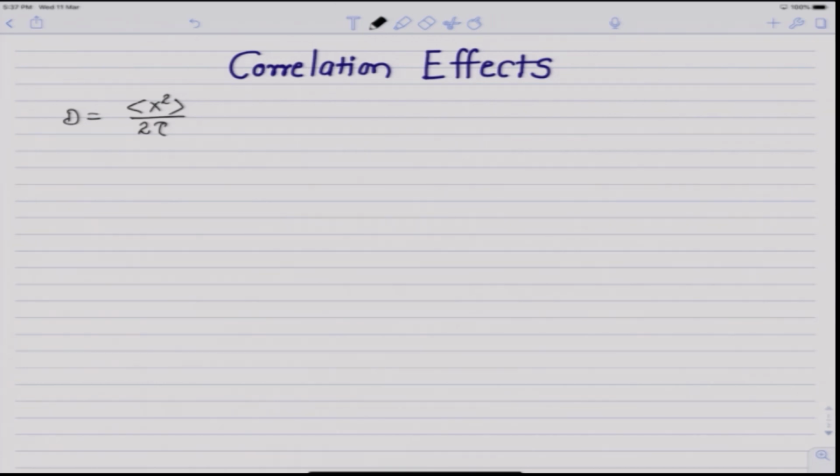If we consider the mean square displacement, which is denoted as average r square, it can be given as average of x square plus average of y square plus average of z square. x, y, z here denote the projections on x, y and z axis of the net displacement vector r. In isotropic diffusion, the distribution is spreading equally in all directions.